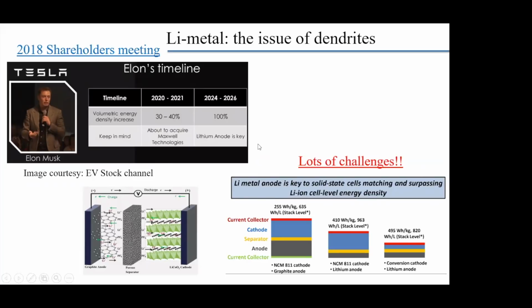They're constantly working on increasing the energy density, right? This is from the 2018 shareholders meeting. A nice channel called EV Stock Channel put out this cartoon. And Elon mentioned that in the near term, they can increase the energy density by 30%. And right after that, in early 2019, they acquired Maxwell Technologies. But for the long term, if you really want to push it to 450 or 500 watt hour per kilogram, there's one thing that is absolutely key, without which you really can't push it beyond 400, up to 500. That is lithium anode.